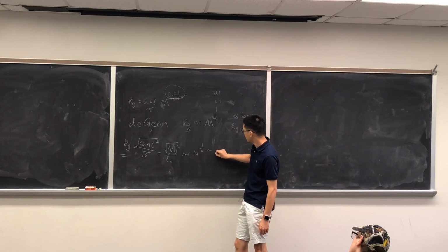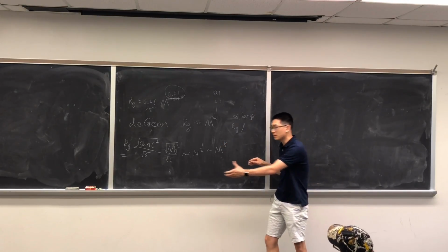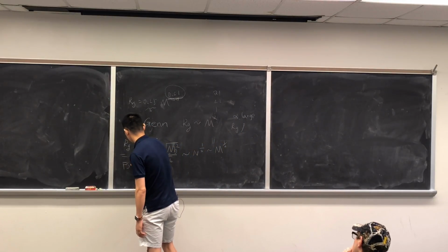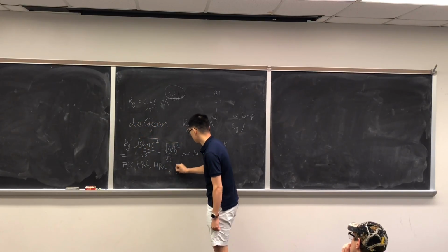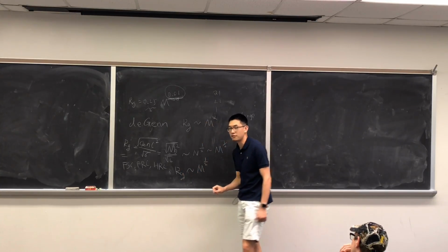Basically, if you multiply by molecular weight, you get n to the power of 0.5. So what does this mean? In the free joint chain, free rotation chain, or even hindered rotation chain model, your Rg is always proportional to molecular weight to the power of 0.5.